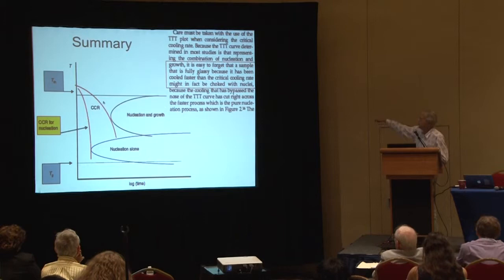This was a summary of this. It's easy to forget that a sample that is fully glassy because it's been cooled faster than the critical cooling rate might in fact be choked with nuclei. That's a take-home message. And when we reheat this, all these nuclei have to do is grow. They don't have to jump over any energy barrier of the type that Vale was showing us, but they just have to grow.